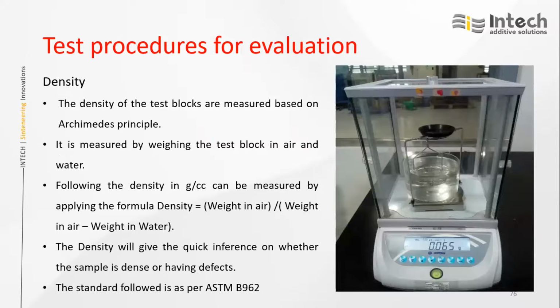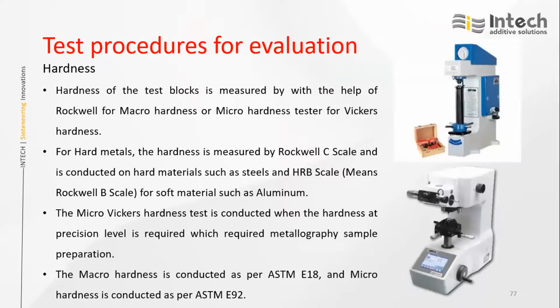Density measurement is as per the Archimedes principle. It is calculated based on weight in air divided by weight in air minus weight in water. The standard which we follow is ASTM B962.